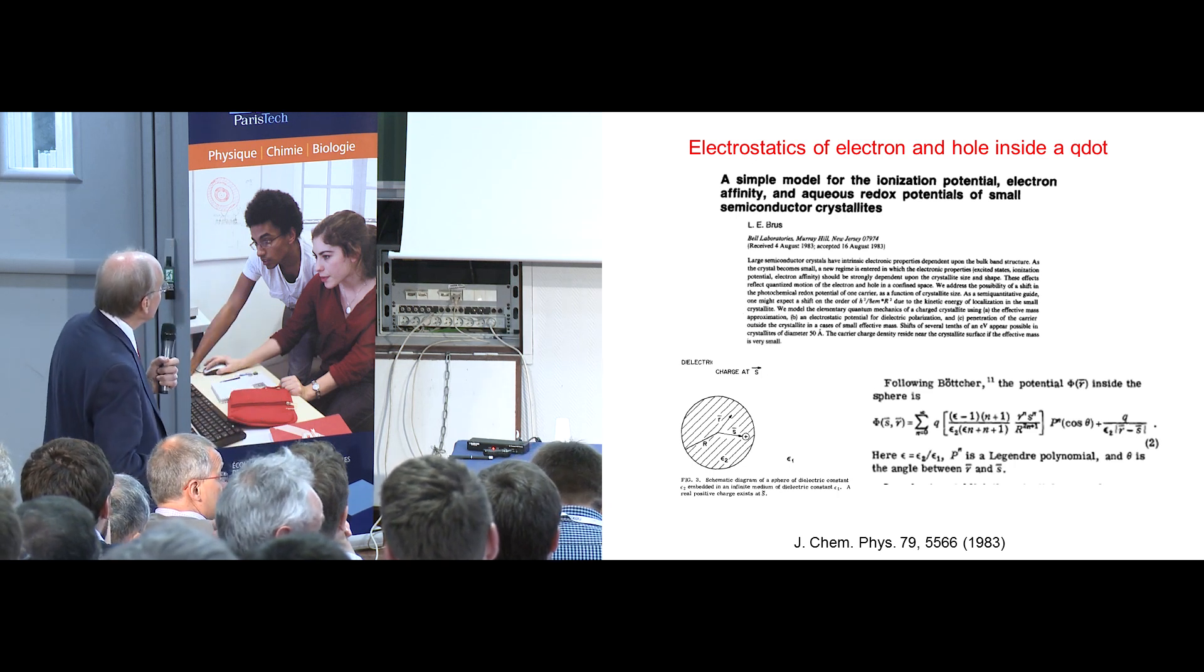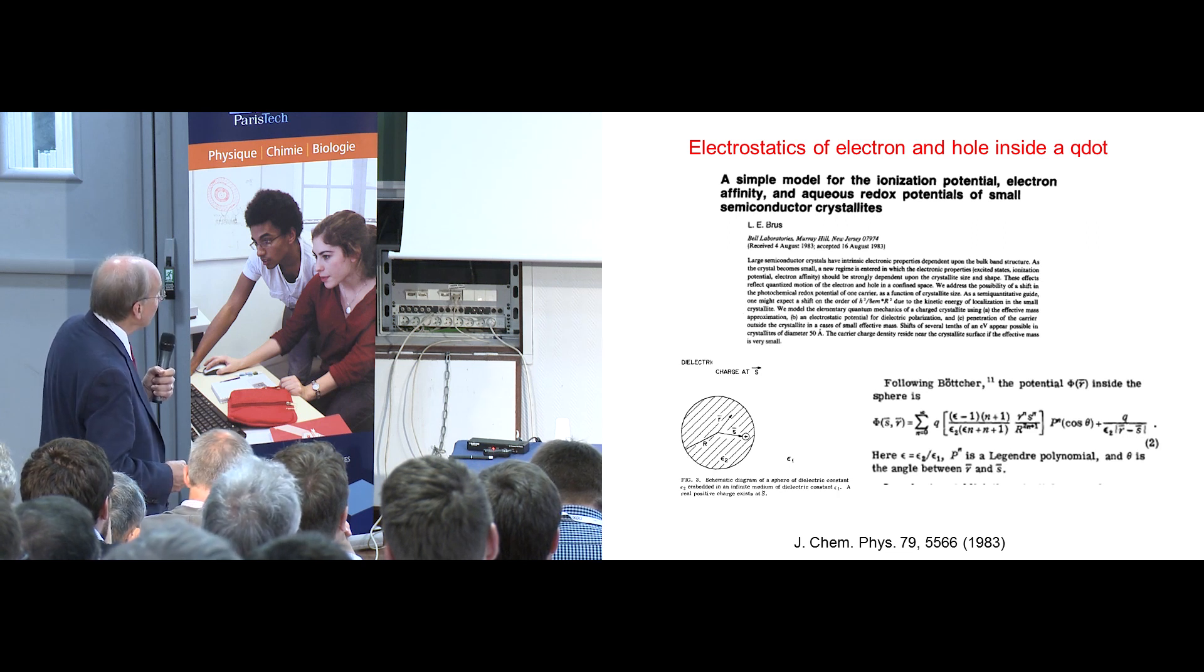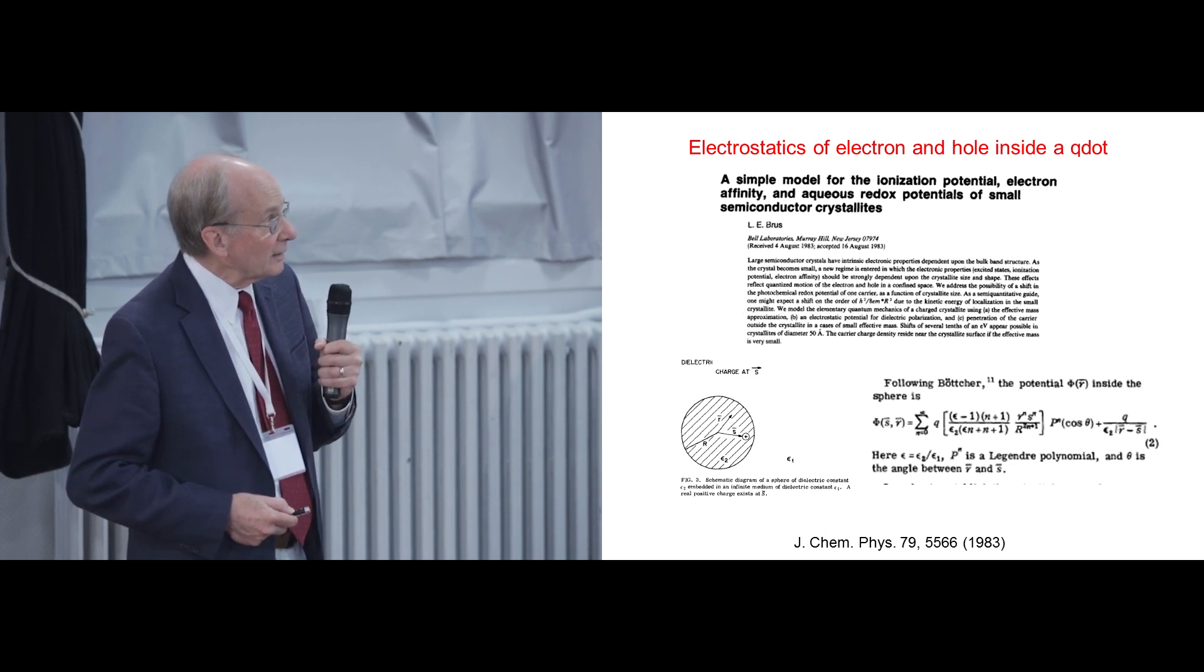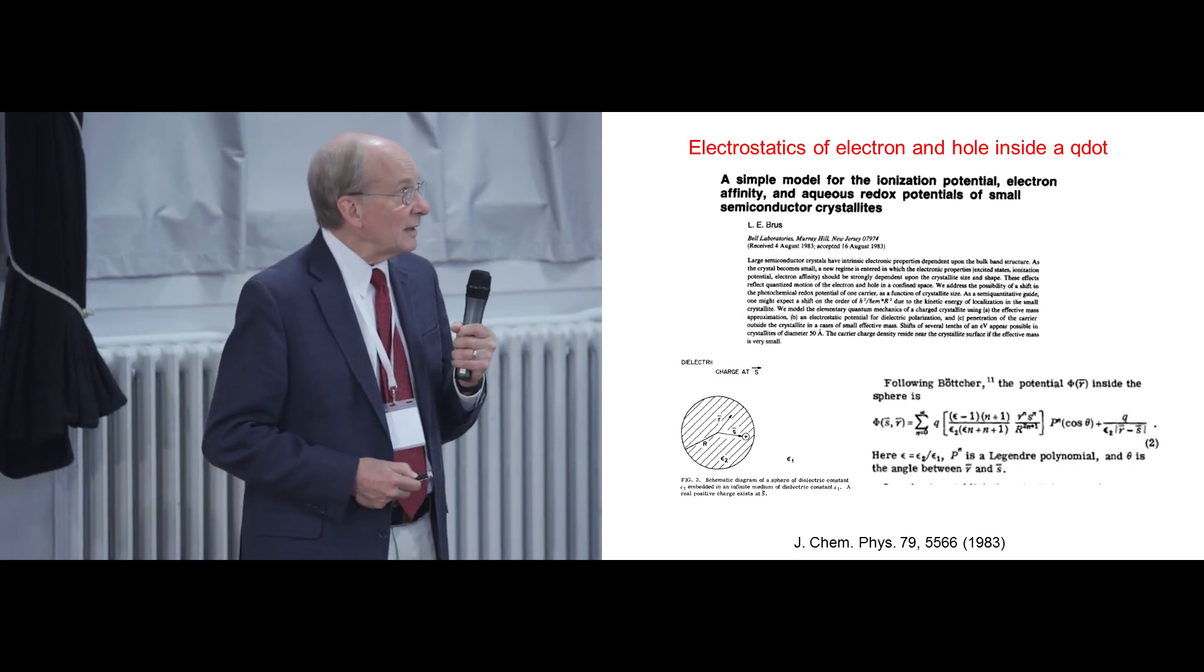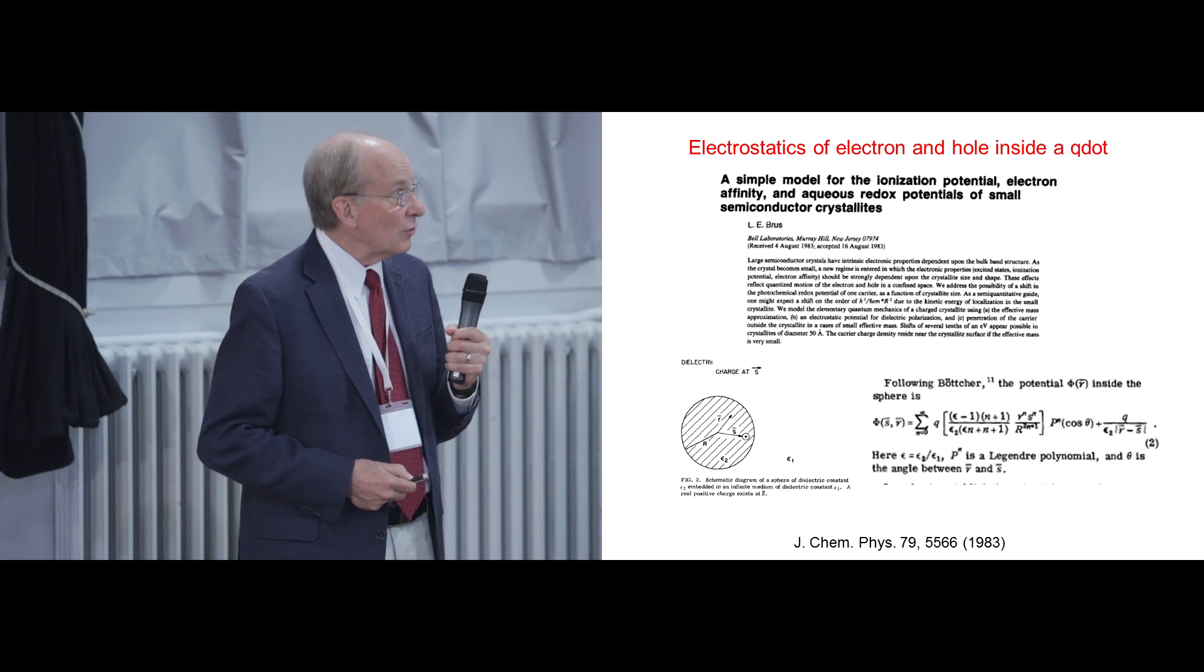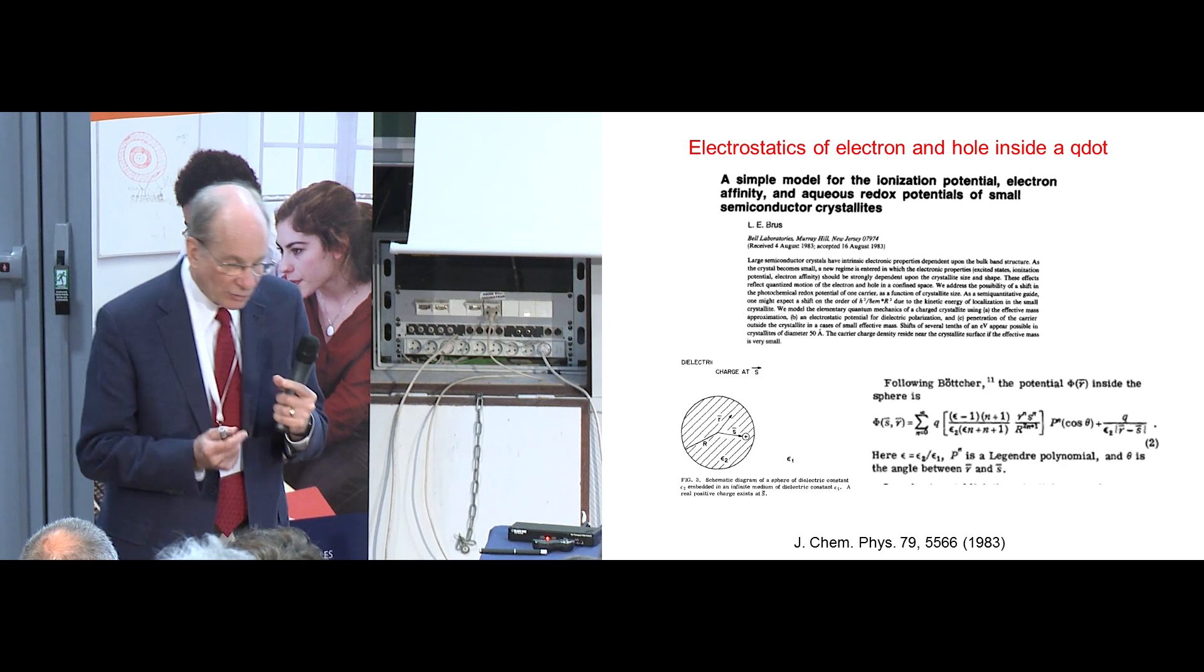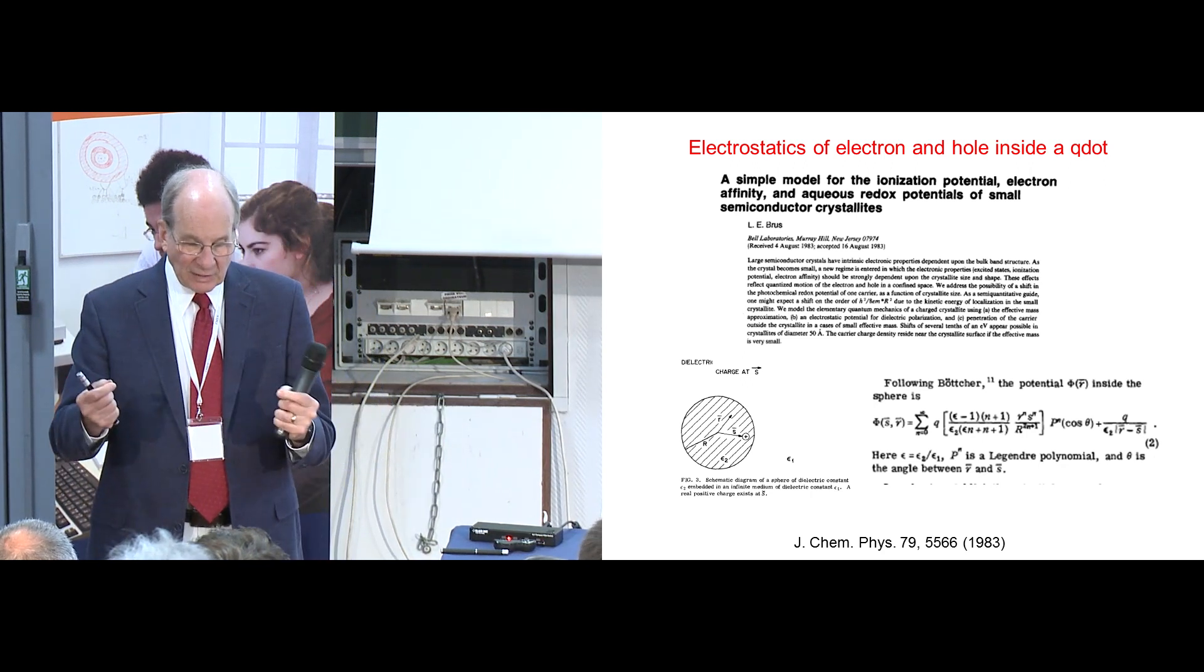So we worked out basically the solvation energy for, in this case, you can see the formula for a single real charge, positive charge, in a dielectric sphere of high dielectric constant surrounded by a region of low dielectric constant. This would give the dielectric solvation energy for one charge in a nanocrystal.